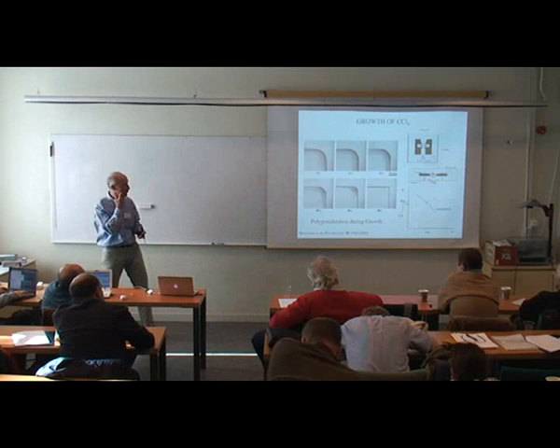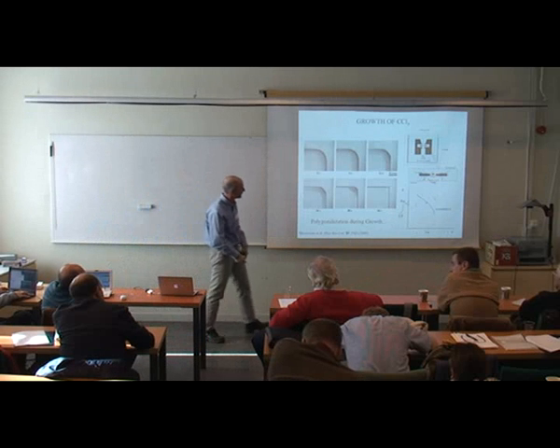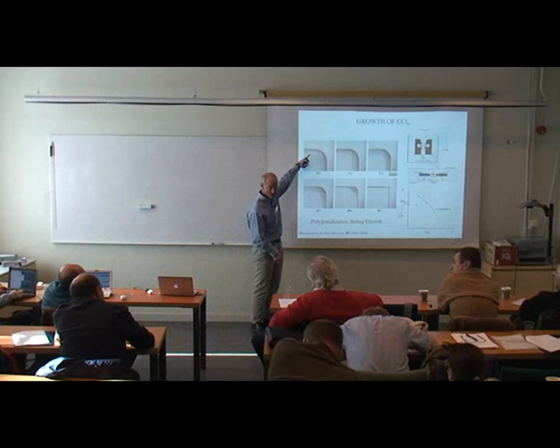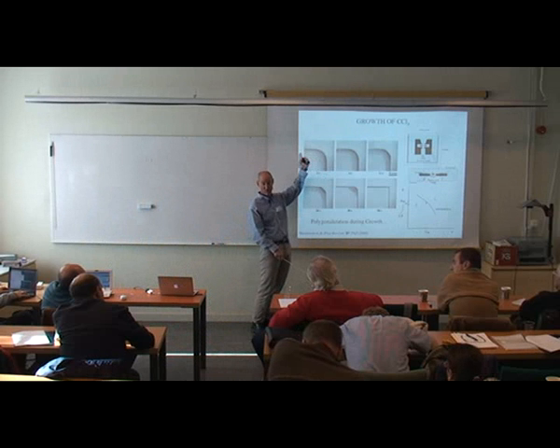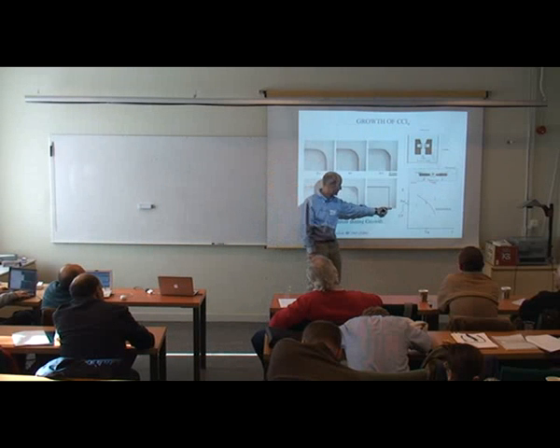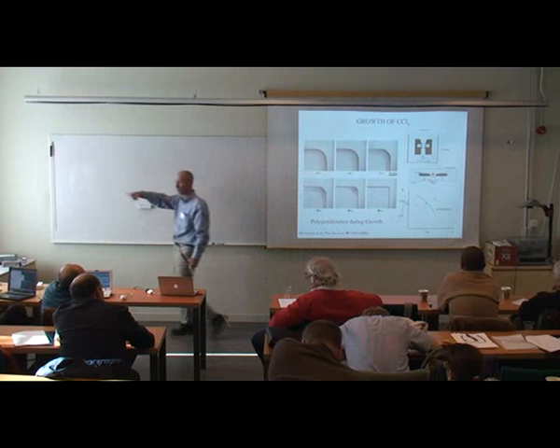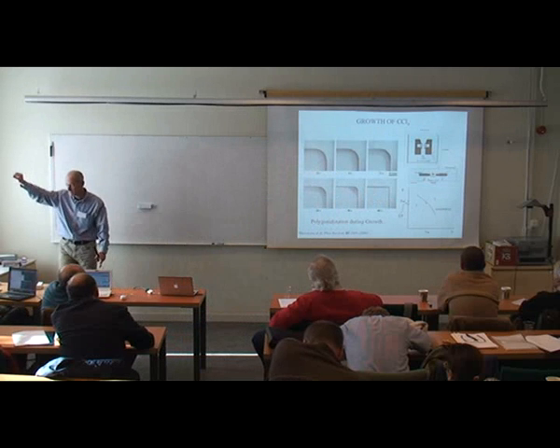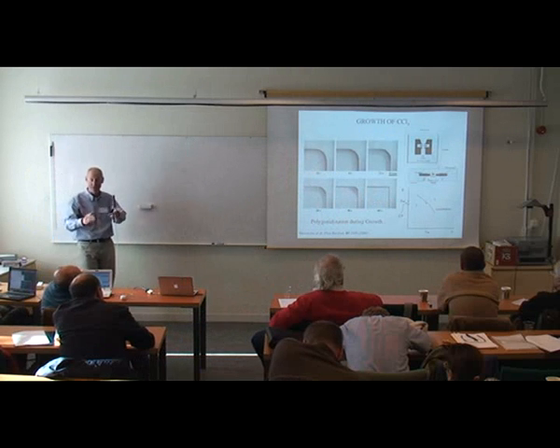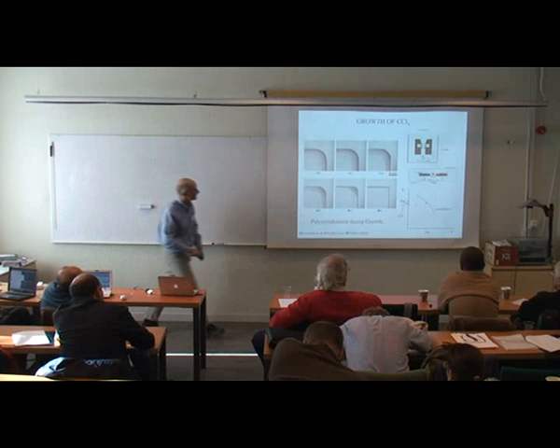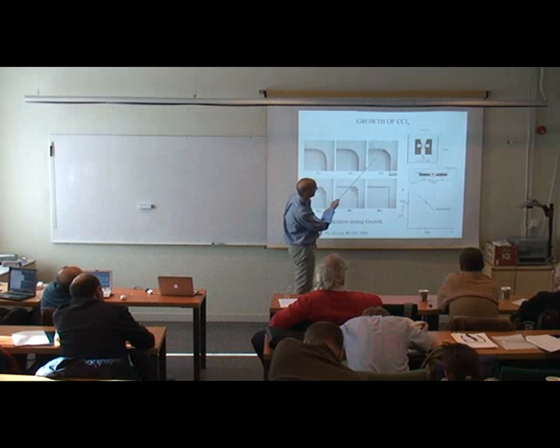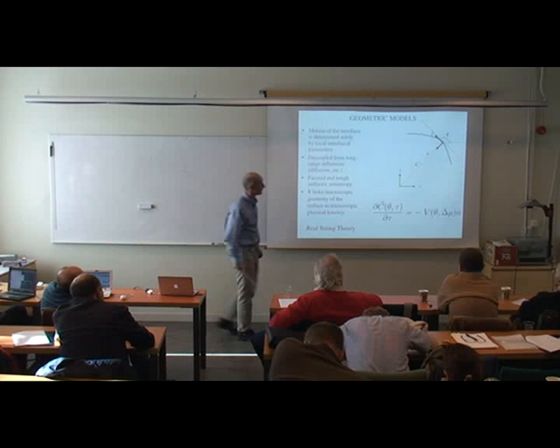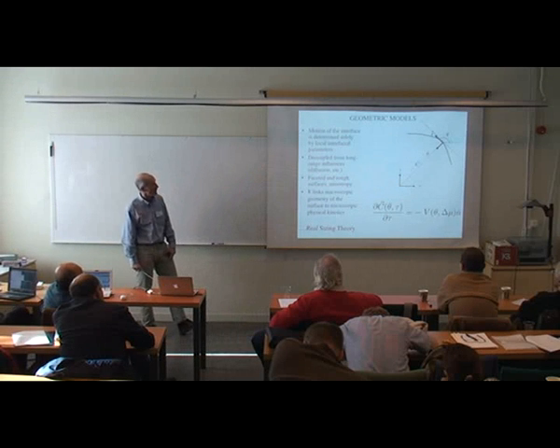And so a target for theory is to say, well, look, there's two ways I can go from this state that has all orientations between 0 and pi over 2, to this that only has 0 and pi over 2. Okay? One is that I can have a continuous increase in curvature until I add the last atom. And the other is that I can have regions that increase in curvature and regions that decrease in curvature. Okay? And those are associated with where I get discontinuities in the surface slope. Okay, so how do we understand that?